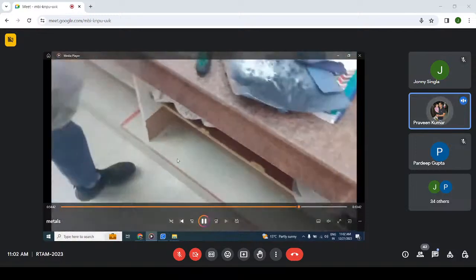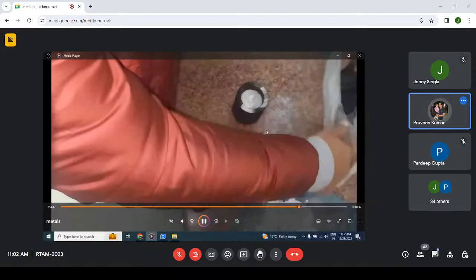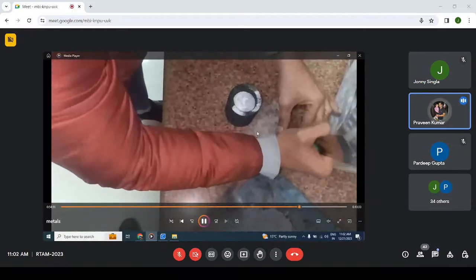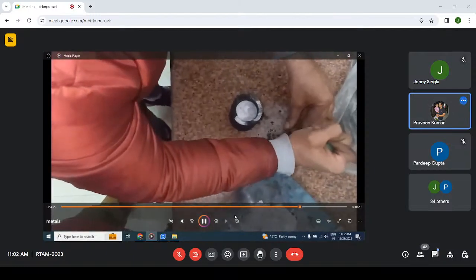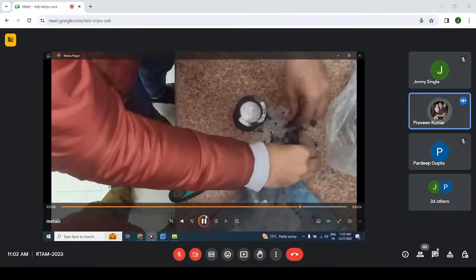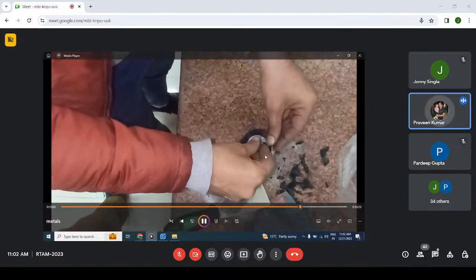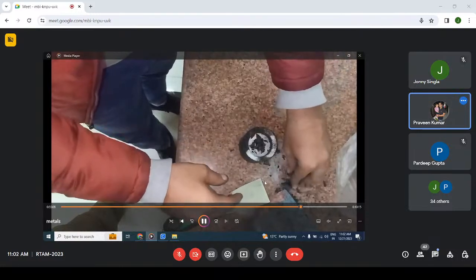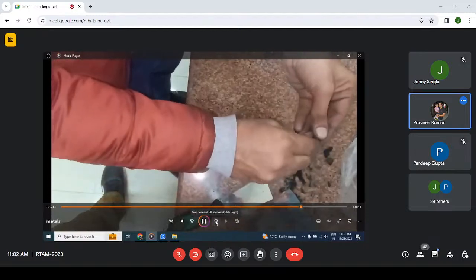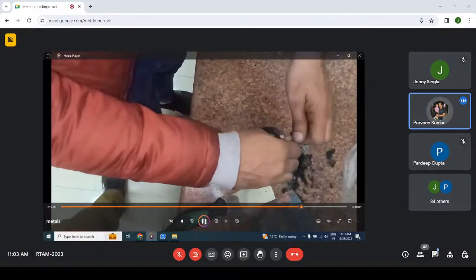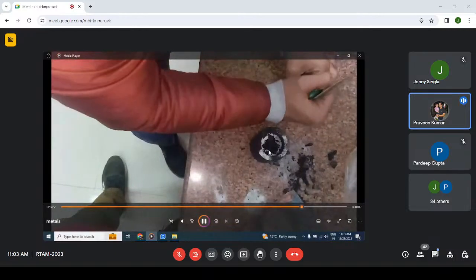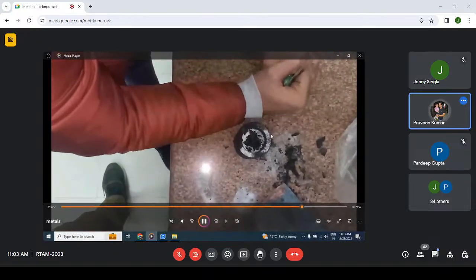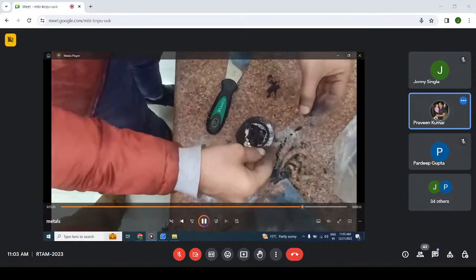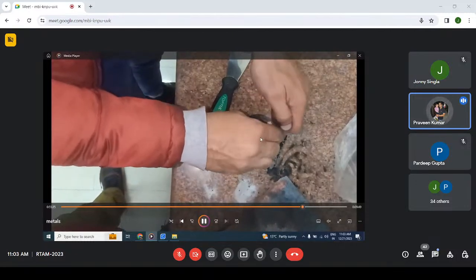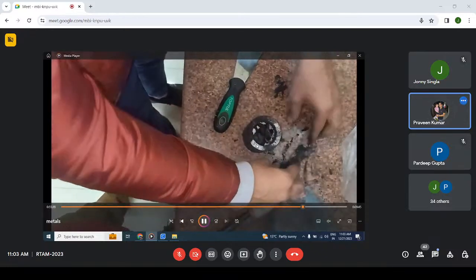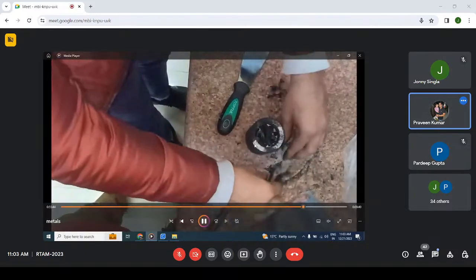After covering the object with aluminum oxide, now I'll cover it with another layer, which is a carbon layer. We'll take coal and crush it into small particles, and spread it over this aluminum oxide in the crucible. These coals are spread over the aluminum oxide so that the direct heat of the sintering oven won't disturb the object. It will first give heat to the coal, and the coal heat will transmit to the object. So we'll cover it very gently.